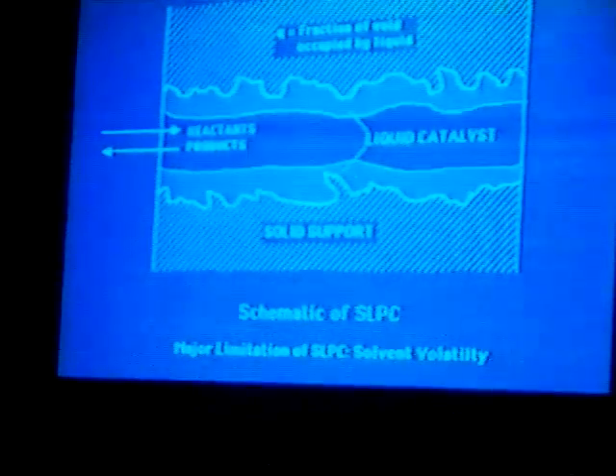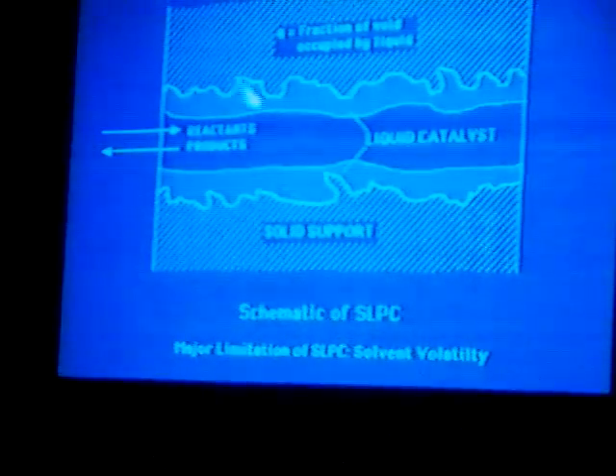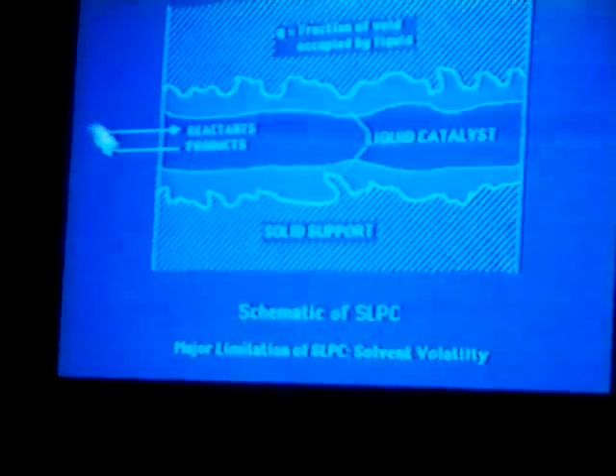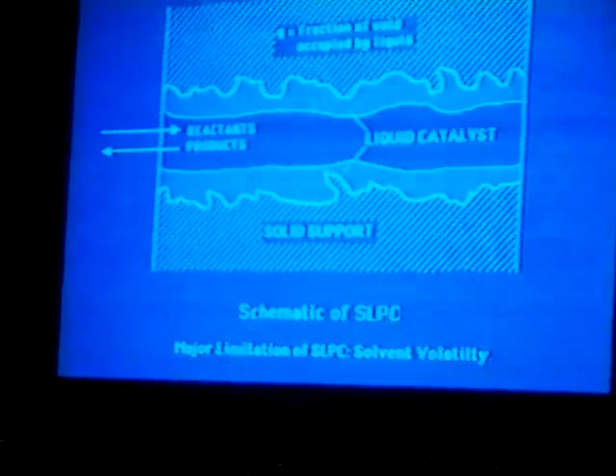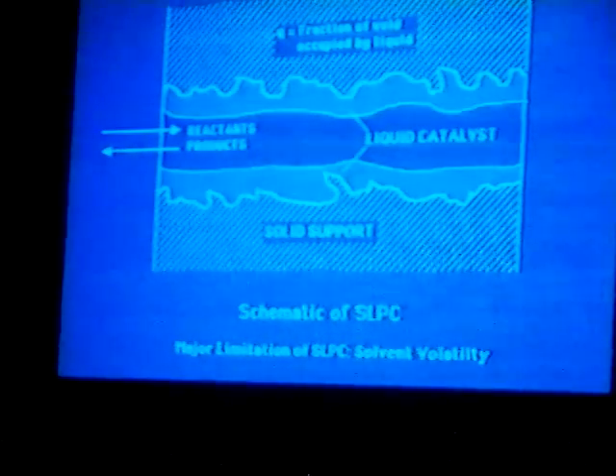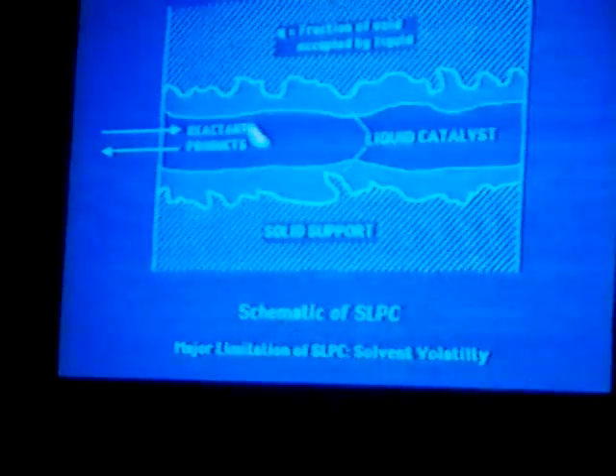This is a schematic of supported liquid phase catalysis, with the acronym SLPC. It is just like a heterogeneous catalyst except that instead of depositing the heterogeneous catalyst on the surface of the porous support, you coat the surface with a thin liquid film which contains the homogeneous catalyst. The pores are not filled completely — there is a residual gas pore space where reactants can diffuse in and products diffuse out. There is a factor Q, defined as the fraction of void volume filled by the liquid. When Q equals one, the entire pore space is filled, causing serious diffusion limitations, so you clearly don't want Q equal to one.